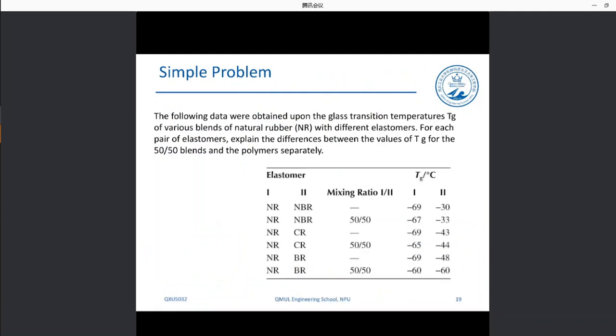A very, very simple problem. We have this table, with data that show the glass transition temperatures of different blends of natural rubber, NR. So elastomer 1 is natural rubber, blended with different elastomers. Have a look at the table and please let me know what you observe in terms of the difference between the values of the Tg for the 50-50 blends, and what conclusion you can draw. Let's focus on those three where we know the mixing ratio. What happens with these three blends? Please text me on WeChat to let me know what you understand is happening in these blends.